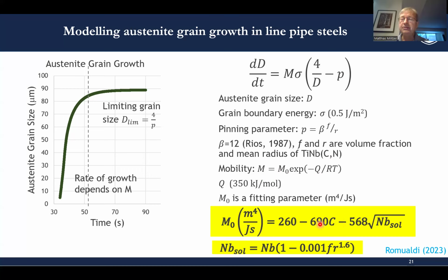The role of carbon seems to be inconsistent with what I had just shown for these model alloys, but we have here to consider that carbon interacts with many alloying elements, for instance, manganese, and it could be that it kind of leads to some co-segregation of these additional substitutional elements, and that's actually the reason why we see this apparent effect of carbon in terms of reducing the effective mobility of the boundaries.